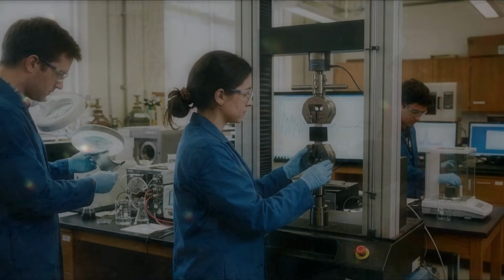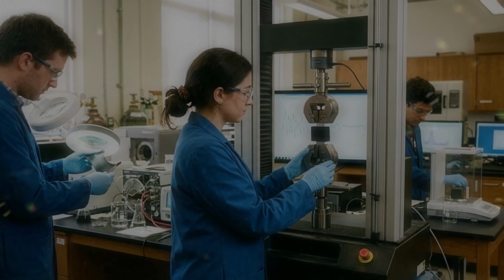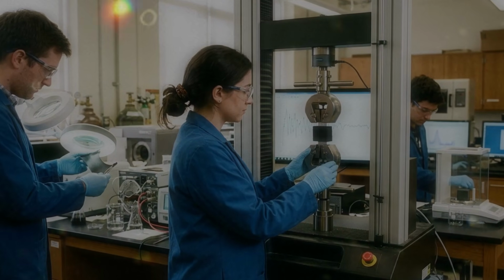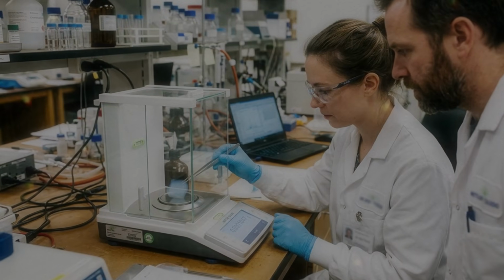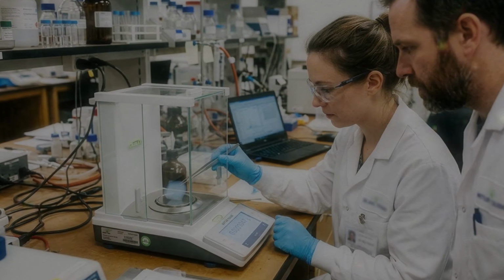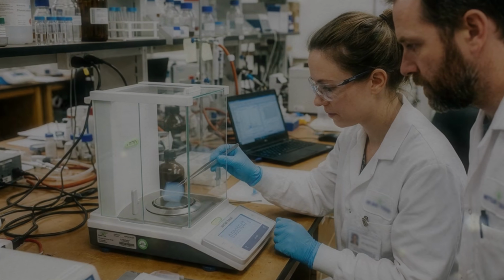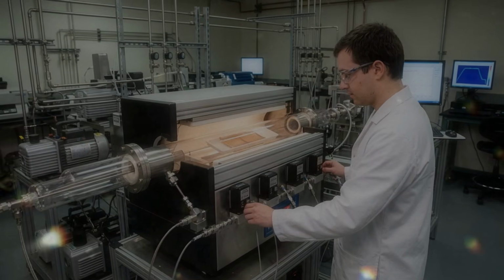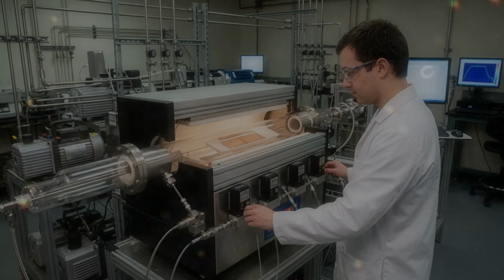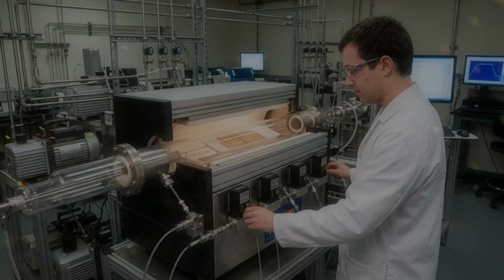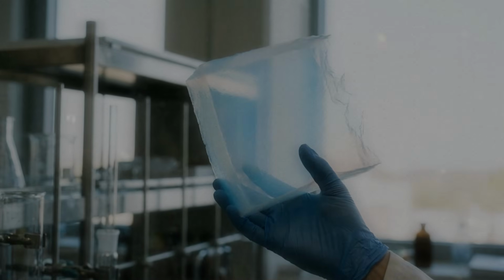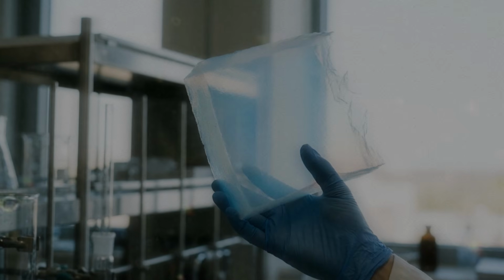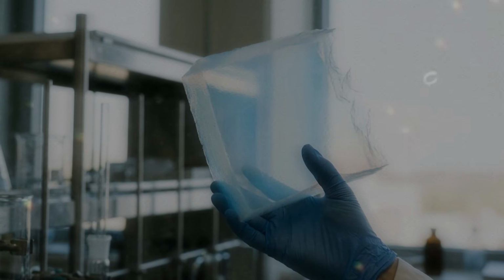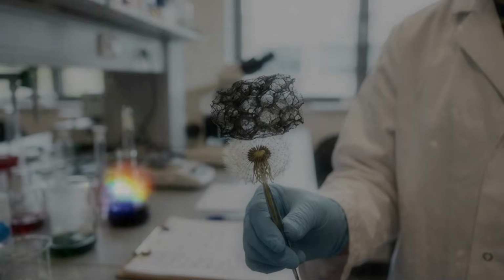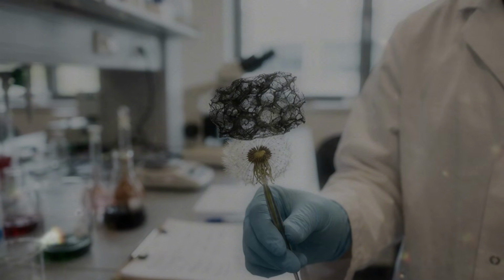Some forms of aerographene have been produced with a measured density of about 0.16 milligrams per cubic centimetre. Air near sea level has a density of roughly 1.2 milligrams per cubic centimetre, although the exact value changes with temperature, pressure and humidity. This means that the measured density of the ultralight carbon framework can be around 1/8 of the density of the surrounding air. That statement needs careful handling. It does not mean that a piece of aerographene will behave like a helium balloon and rise toward the ceiling.